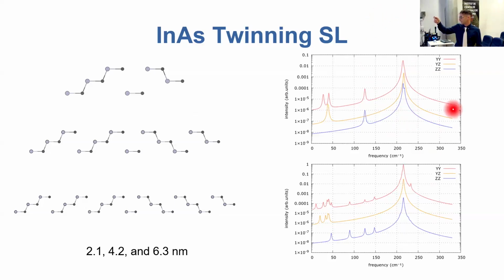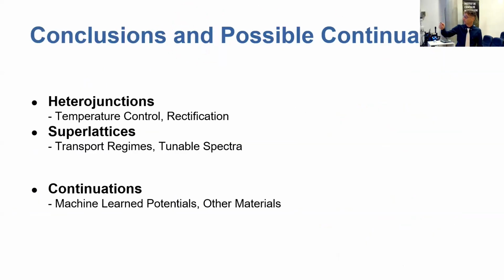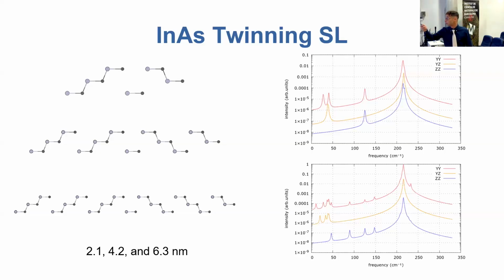You can see in a completely evident fashion the principal peaks which correspond to the optical frequency of indium arsenide, and then you can see how modifying the superlattice period, so introducing longer and longer primitive cells, leads to the appearance of new optical modes adorning basically the principal peaks of the indium arsenide material. And this is very interesting because it proves that also twinning superlattices can be used as a means of engineering the phonon spectra and the optical and thermal transport properties of a given material, not only the chemical ones.